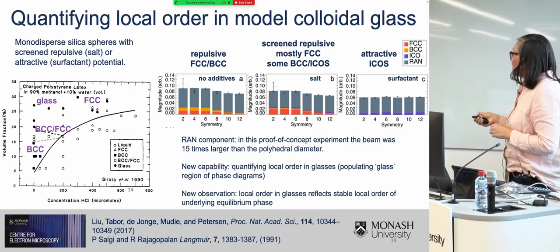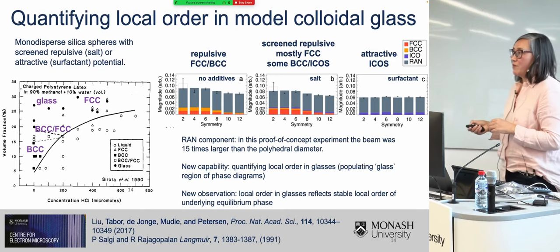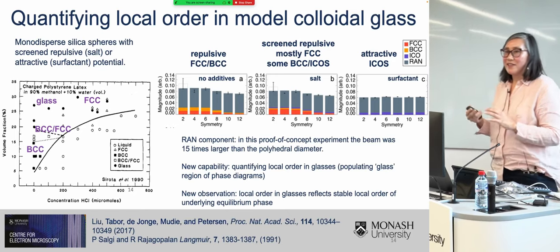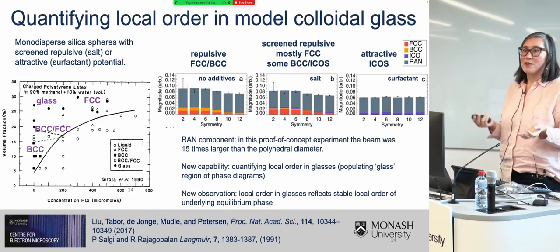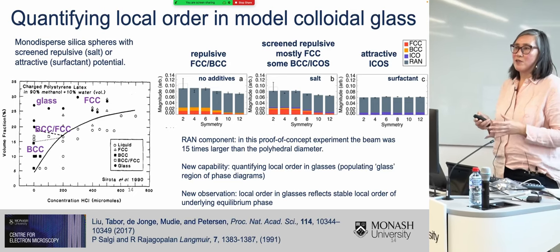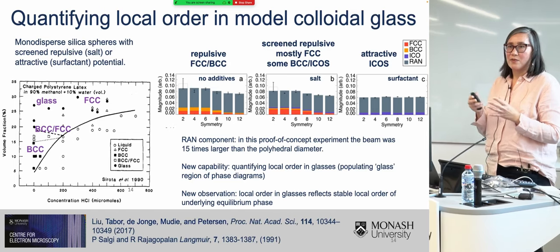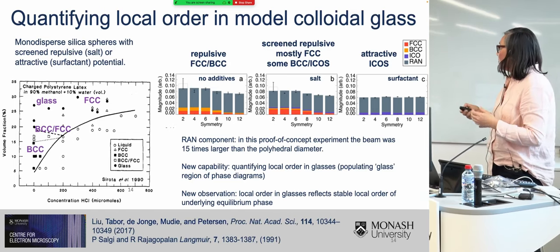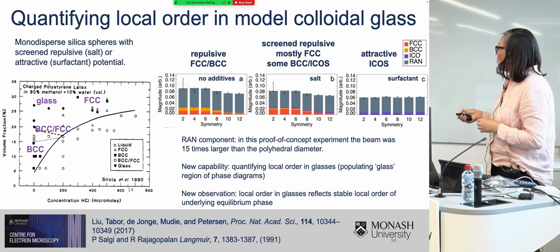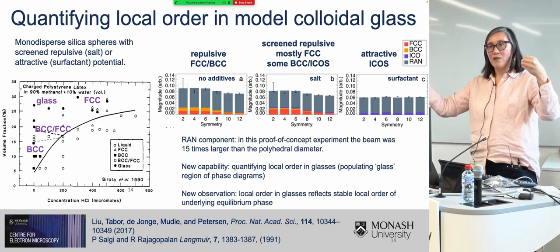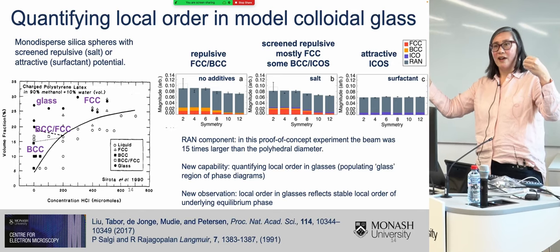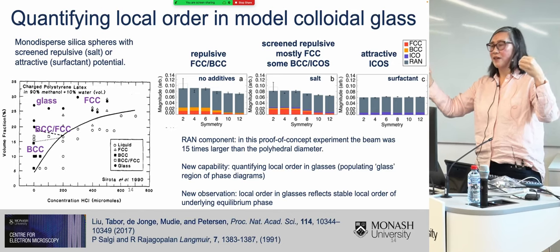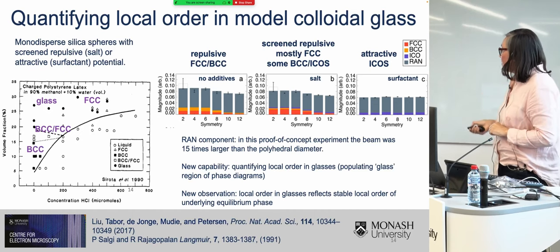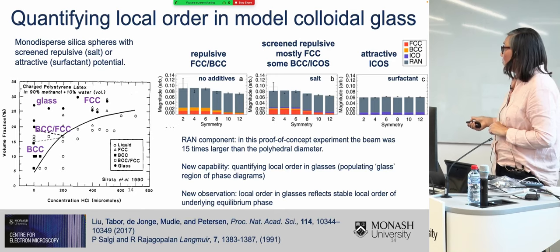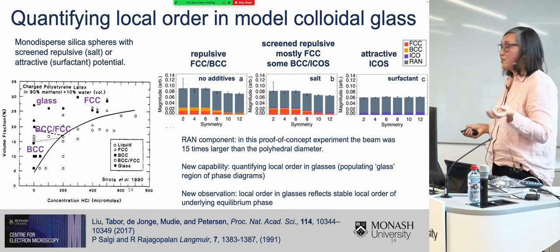Now, you might be wondering, what is this large grey component here, which I've labelled RAN? Well, that is because, unfortunately, for this proof of concept experiment, the aperture I used was 15 times the size of a polyhedron. And so this large RAN component is from clusters that are too far away from each other in the aperture, giving rise to uncorrelated diffraction. But nevertheless, we've identified a new kind of capability, which is quantifying local order in glasses from diffraction alone.